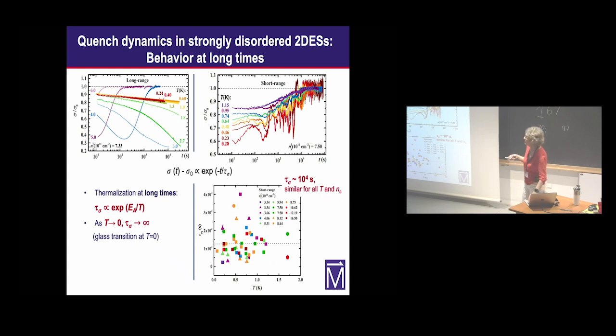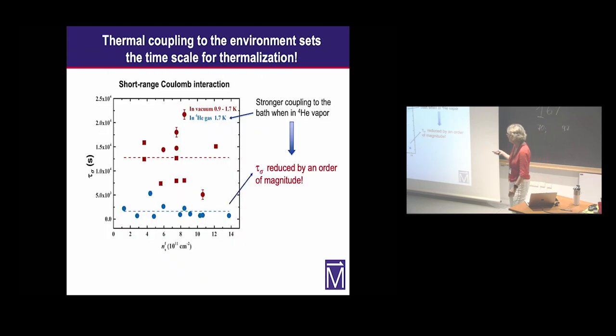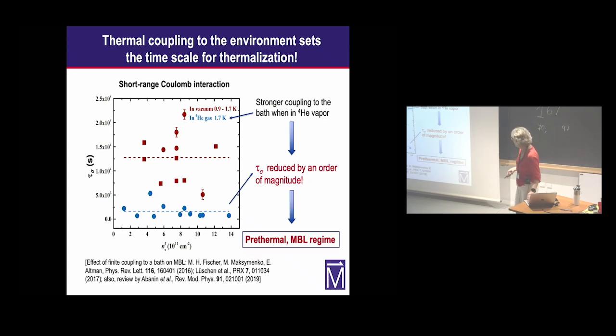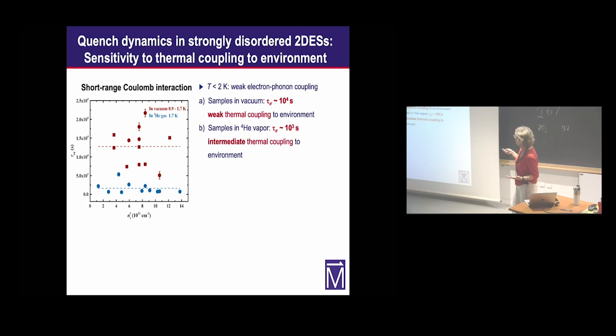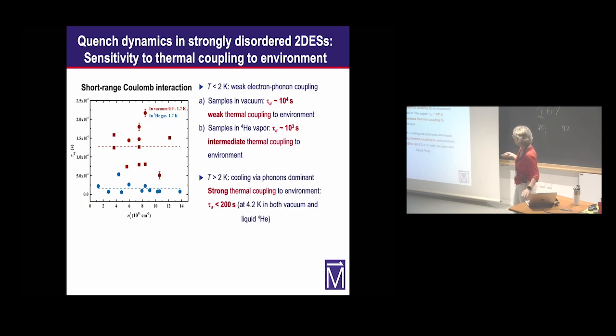We can do that, for example, by repeating some of the experiments in helium vapor, which is what we did. And when we did this, we saw that these 10,000 second thermalization times were reduced by an order of magnitude, which is again consistent with the expectations for MBL. These measurements were done below 2 Kelvin, where electron-phonon coupling is very weak. You can go to higher temperatures where cooling or thermalization by phonons dominates, and we found that the thermalization time dropped by at least another order of magnitude.